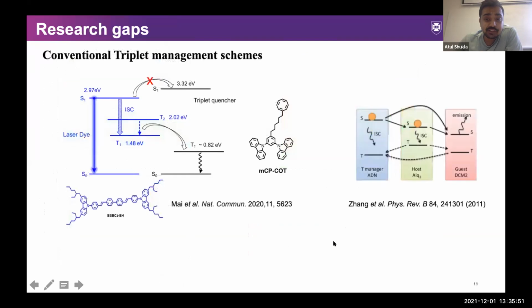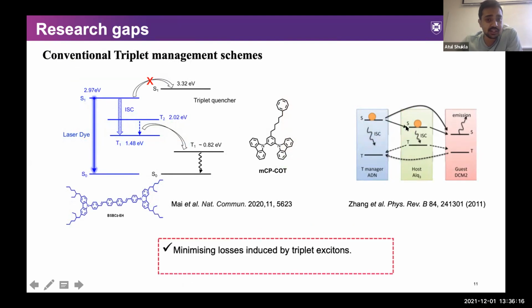So looking at previously utilized methods for triplet management, this includes the use of triplet quenchers. This was shown by one of my colleagues earlier last year, using COT as the triplet quencher. And previously this was shown by Professor Stephen Forrest's group, again, using ADN as the triplet quencher. So this technique works really well in reducing the losses, but the problem is that it doesn't utilize the triplet excitons. And as we showed earlier, even if we reduce the triplet losses, the thresholds are still very high for these materials.